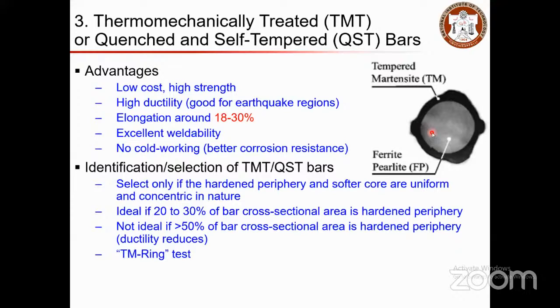When you need to select TMT bars, you need to select only if the hardened periphery and soft cores are uniform and concentric. So when you do the check, I will explain the TM ring test as well. When you do the TM ring test, you need to have the TM ring formation on the outer surface, and you need to have this FP phase in the core. But it should be consistent. So there should be an allowable range.